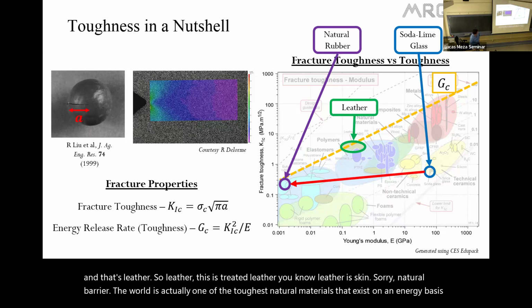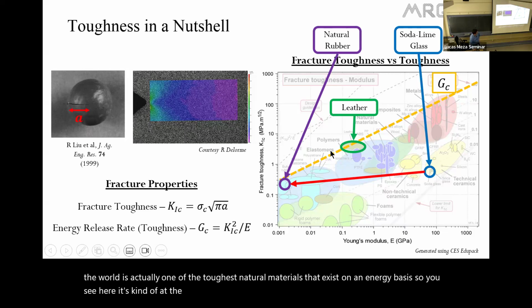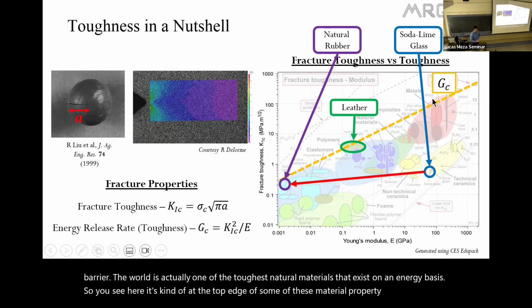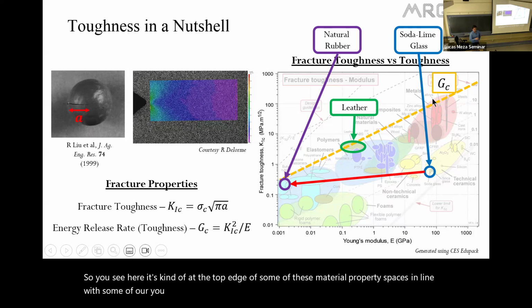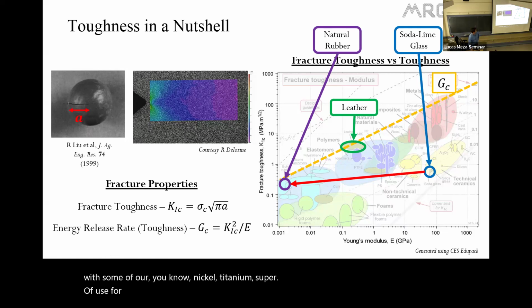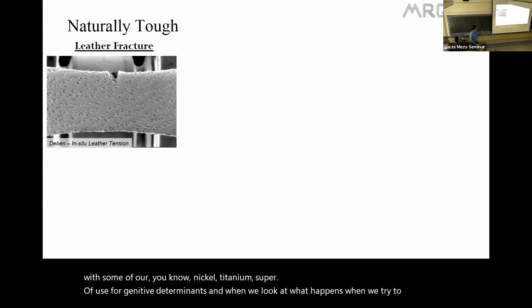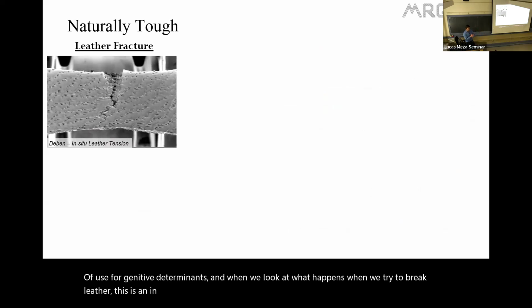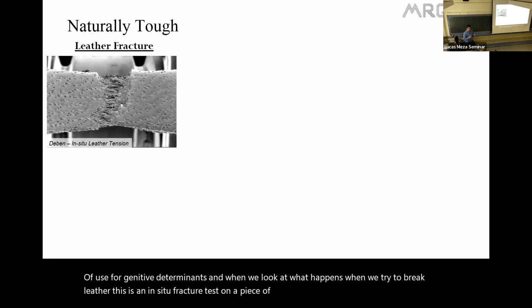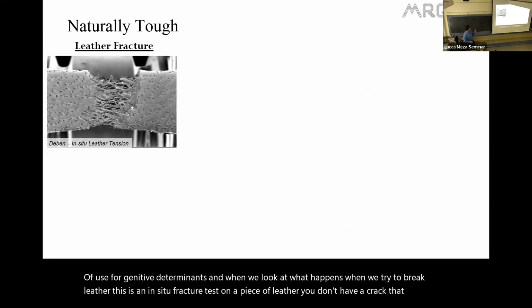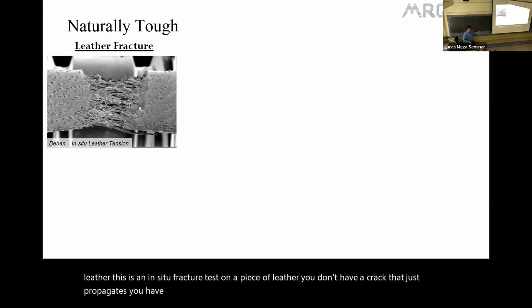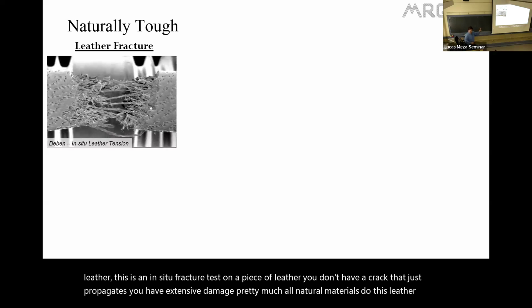So you see here, it's kind of at the top edge of some of these material property spaces, in line with some of our nickel titanium superalloys that we use for jet engine turbines. And when we look at what happens when we try to break leather, this is an in situ fracture test on a piece of leather. You don't have a crack that just propagates. You have extensive damage. Pretty much all natural materials do this. Leather is remarkable in its ability to do this.